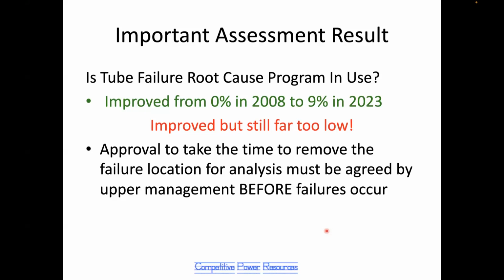In 2008, none of the sample plants had a program in place to do this. Today, only 9%. So that's an improvement, but it's still far too low, which tells us that most operators have a failure and then they do not follow through, take a sample and do the root cause assessment. So they find themselves subject to repeated failures from the same cause.